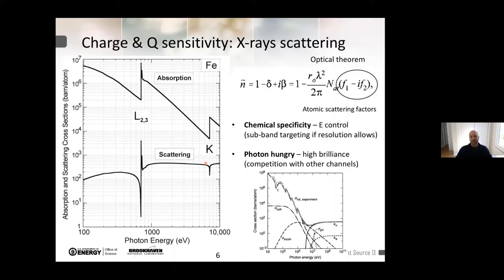And so we decided to go to X-ray scattering, because it's well known that everything, let's say, at the microscopic level relies on the atomic scattering factors. We have chemical sensitivity, we can have site sensitivity. It's certainly a very photon hungry technique, because it competes with other prevalent phenomena, at least in the energy scales where we want to sit if we use soft X-rays, but essentially over all the spectrum available at synchrotrons. So it's of course not a prevalent factor. However, it's enough to extract quite a bit of information, as we will prove.